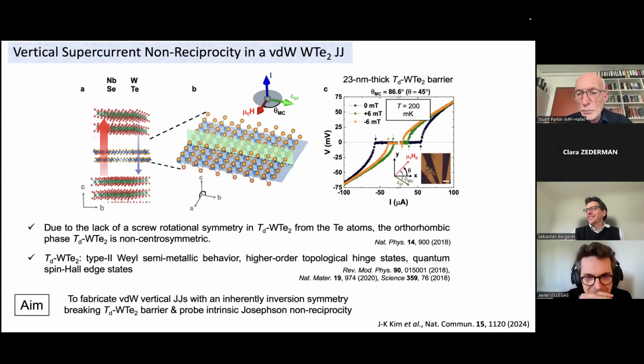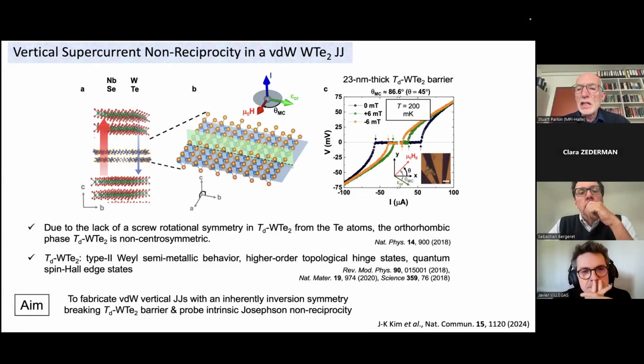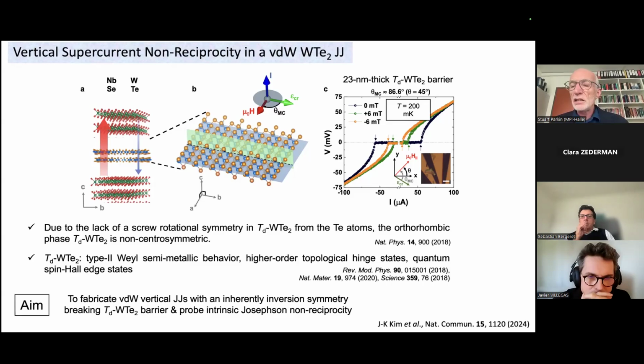So here's the example where we see a diode effect. And the diode effect for the green and orange curves, as we change the field from plus 6 millitesla to minus 6 millitesla, you can see that the difference, the diode effect that we see, has changed its sign. So what does it mean?